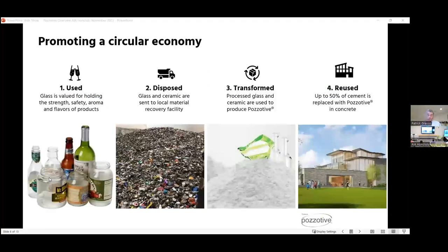We think it's a great circular story to tell. We're taking local glass. I wish that first photograph is what we get, that clean, but that's what you put in your recycling bin. When it goes to the material recovery facility and gets co-mingled and separated, that's what we get, and that's what is being called glass delivered to us. And that's the challenge, the paper, plastic, metals, cardboards that remain in there. Our job is to clean that to a very high standard, 99.5% or better purity, to mill it to that fine powder you see, and then put it back in the communities from which it came.